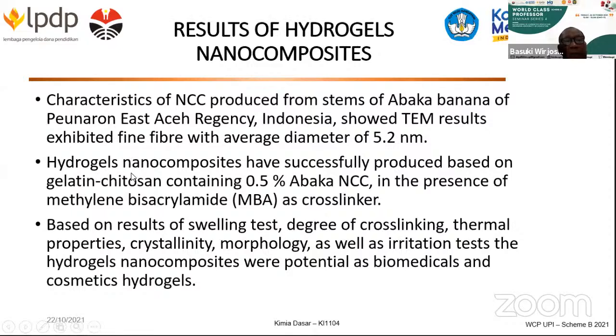And we produce also hydrogel here. The hydrogel is based on gelatin and chitosan containing only 0.5% of nanocrystal cellulose. And we use a cross-linker, methylene bisacrylamide. We tested the hydrogel based on the swelling test, also degree of cross-linking, thermal properties, crystallinity, morphology, and we do also irritation tests of the hydrogel. And from this, we recommend that this is very potential for biomedical and cosmetic hydrogels.